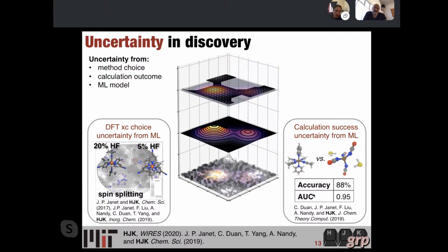But the short answer is one model, as long as you had trained the model, it could just predict new compounds, will they succeed or fail, but with less transferability than the model that used electronic descriptors. And that one, you could change the oxidation state, you could go to a new material space, and that picture of calculation failure was more transferable, but required, in practice, we used up to the first 12 hours of a calculation to decide whether or not to abort.